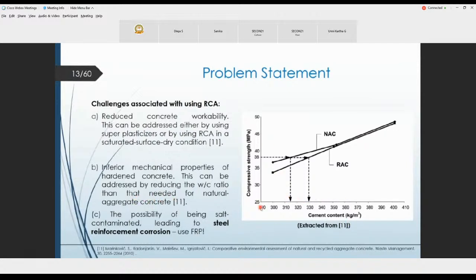You can look here at this relationship between the compressive strength and the cement content for both mixes - one using recycled aggregate and one using natural aggregate. You can see that increasing the cement content from about 313 kilograms per cubic meter to 330 can result in reaching the same compressive strength.